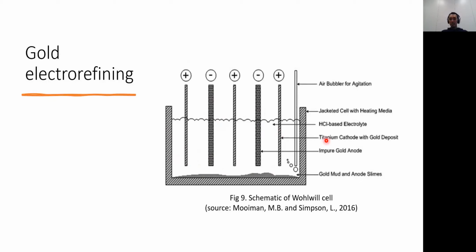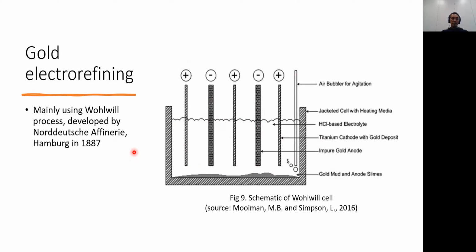onto this titanium cathode. In these pictures it's a hydrochloric-based electrolyte, but mainly people use aqua regia. And then also in the cell, we introduce air bubbles for agitation, to mix the electrolyte to have a steady and homogeneous electrolyte all the time during the process. It was firstly developed by Norddeutsche Affinerie in Hamburg. Now it's called Aurubis. I visited Aurubis back in 2016 with Pekka, if I'm not mistaken.